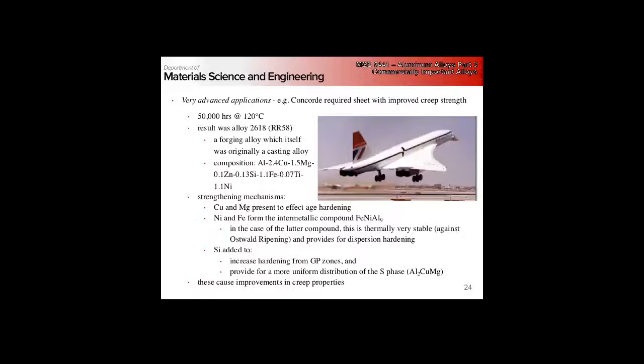So this is kind of cool because we've got copper and magnesium present to affect age hardening. Nickel and iron give us a whole bunch of useful intermetallics. Happens that we get a lot of intermetallics that are particularly thermally stable, so they don't coarsen at these temperatures. Then we get silicon, which gives us additional hardening from GP zones, and helps with the distribution, a more homogeneous distribution of the stabilizing particles.